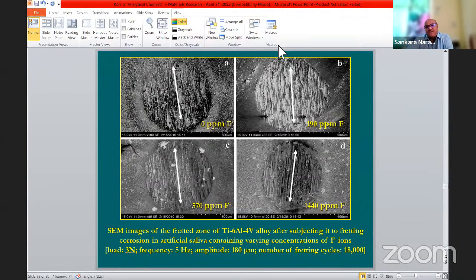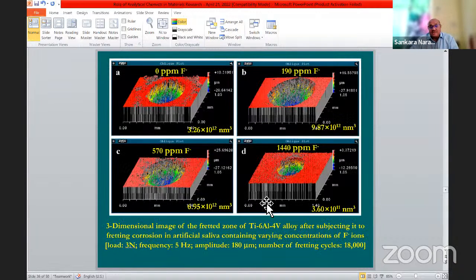There is not much change. The damage is clear, but we could not predict much about the mechanism and how the failure is forming. So in this case, we used the surface profilometer. The advantage of the three-dimensional surface profilometer, which is a non-contact instrument, is that you can observe the image and also measure the depth, the z-axis. In a conventional two-dimensional image, you can measure the x and y axes only. But in a three-dimensional surface profile measurement, you can measure the z-axis also. So we can calculate the entire wear volume that is worn out during friction, during the fretting corrosion. It is completely worn out, and you have created a hole-type structure.